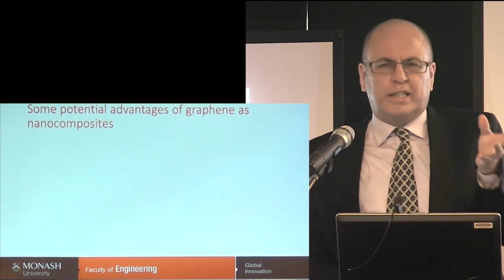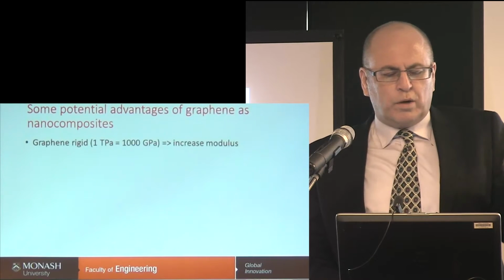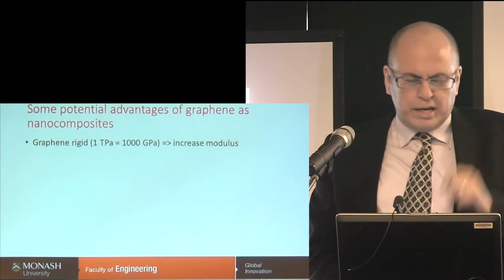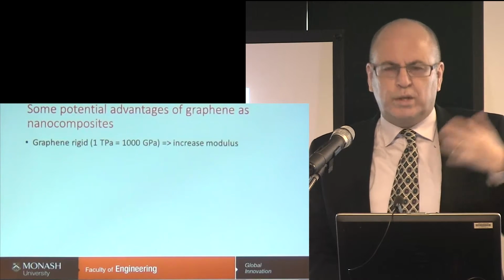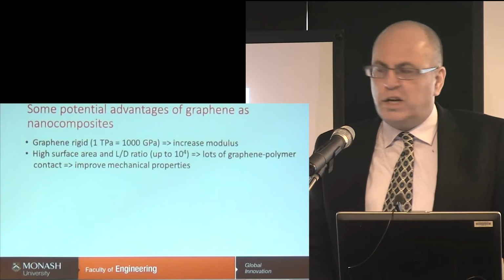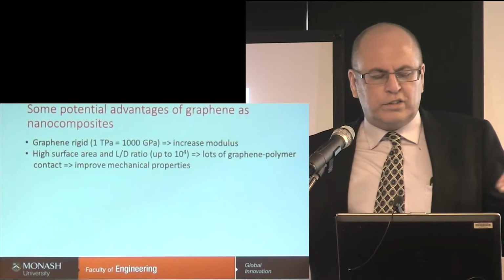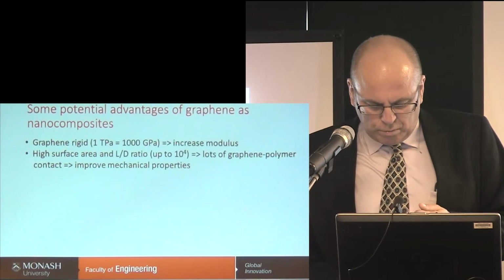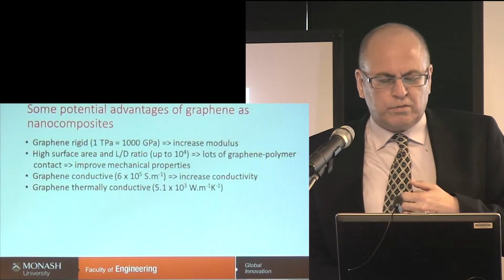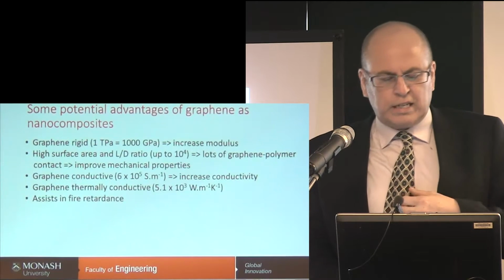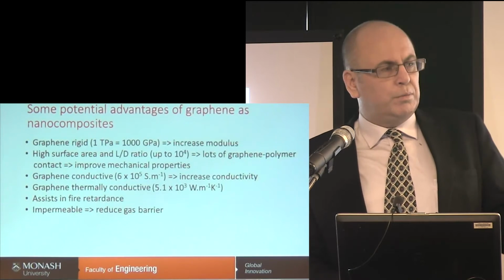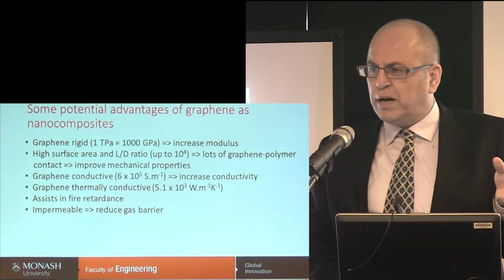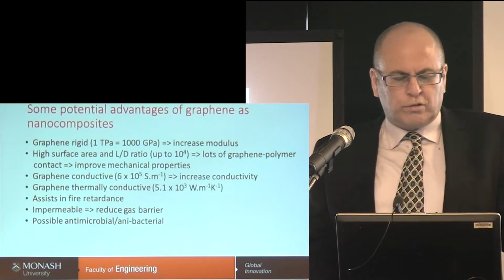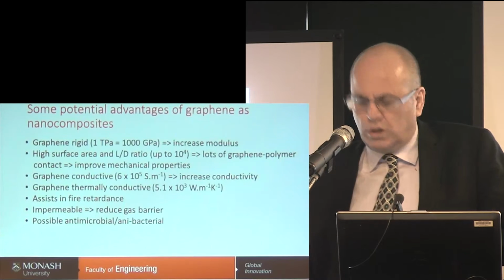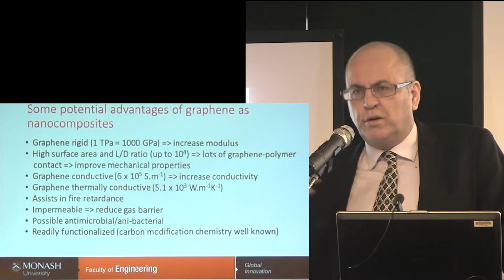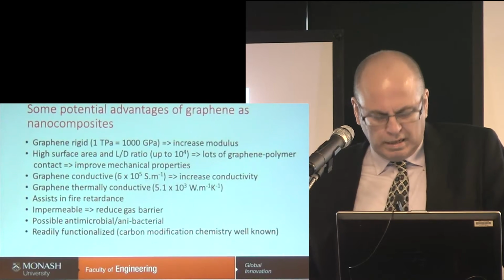So putting that together with the nanotubes and the nanoclays, what are the advantages for nanocomposites made with graphene? Of course, graphene is very rigid, so we can increase the modulus. It has a high surface area, a high L-on-D ratio, if you like. It's very thin, so you can get a lot of polymer contact. You can really influence the polymer properties because of the high surface area. We know it's conductive. That's obviously useful. It's thermally conductive, so not only electrically conductive, it could assist in fire retardancy. It's impermeable, therefore it could produce a gas barrier or even a water barrier. The literature shows that graphene has antimicrobial and antibacterial properties as well. And it's readily functionalised. We know how to functionalise graphene because carbon-based systems have been functionalised before.